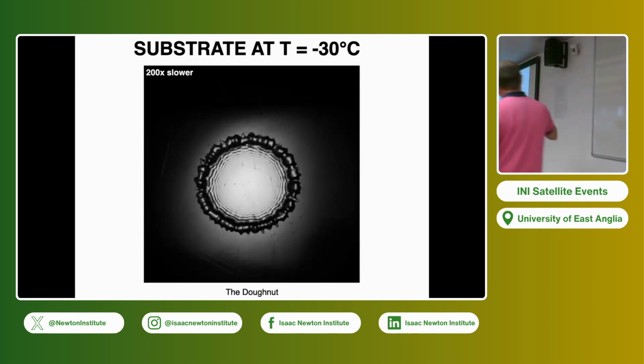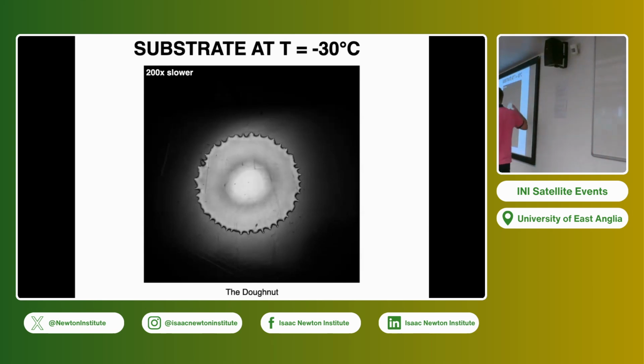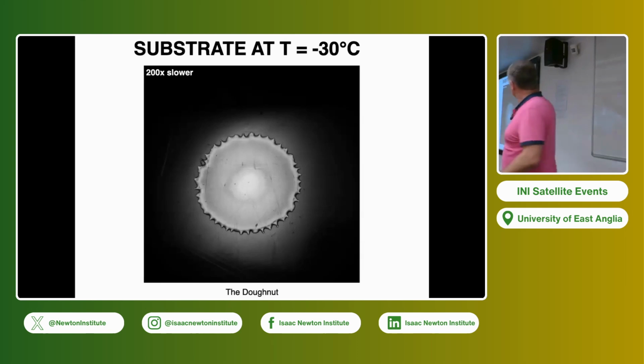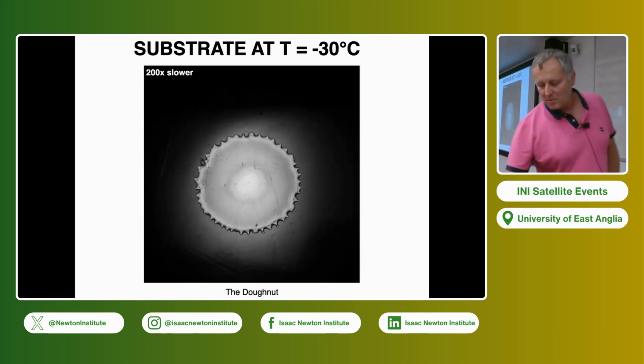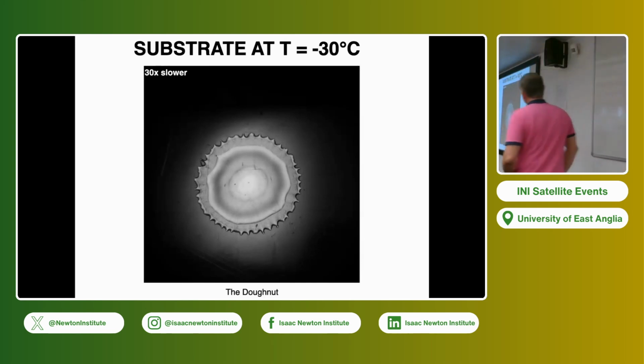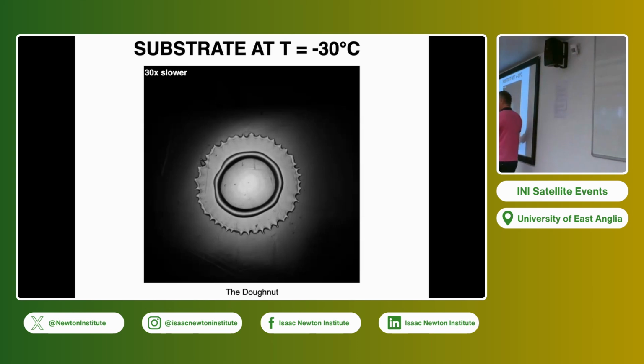Let's go to minus 30 degrees. Again, in the first regime you spread, you are pinned by the contact line, and because of that you have capillary waves to relax from the maximum radius to almost a flat shape of the water, and then again you retract. But now, you retract, but at the same time you are also solidifying, and since you are colder, you are solidifying faster, and you may have a competition between the retraction speed and the solidification speed. In that case, the solidification wins, and you cannot retract until the spherical cap, and you entrap a ring.